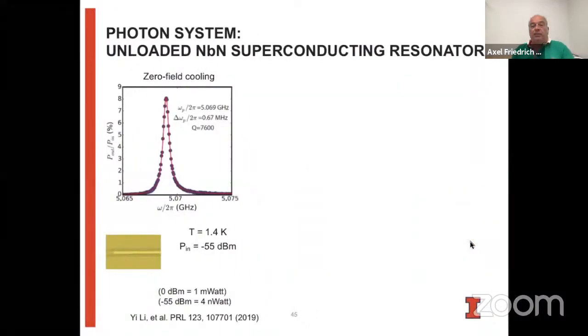So first, let's look at the superconducting resonator on its own. Here you see the transmitted power as a function of frequency. And so we see a narrow peak. The line width is about 0.67 megahertz at a center frequency of roughly 5 gigahertz. So that gives us a quality factor of roughly 8,000. And this is measured at a temperature of 1.4 Kelvin with an incoming power of minus 55 dBm. So it's of the order of nanowatts.